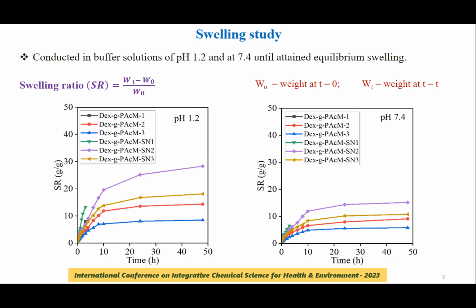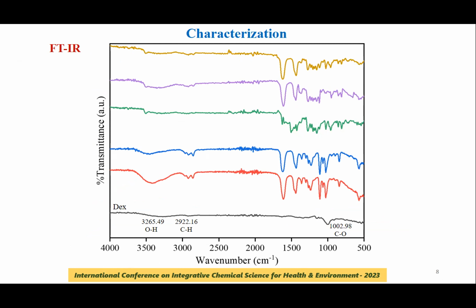Characterization by FTIR: the spectrum of pure dextran revealed the presence of OH, CH, and CO groups. I just mention some unique bands, not all bands. Upon grafting of the monomer onto the dextran, characteristic bands at about 1600, 1400, and 1100 were observed, representing CO, CN, and COC functional groups. Similarly, addition of silver nanoparticles was revealed by the presence of a weak band at about 700 cm⁻¹.